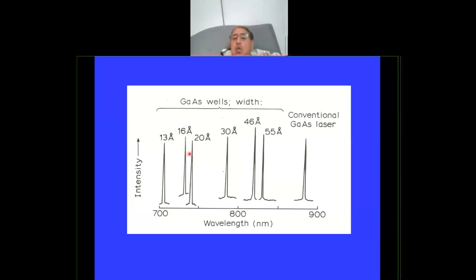Can you imagine if you're making, for example, red lasers or some kind of lasers and you must produce them in this wavelength, 700 nanometers. It means that you have to produce these lasers day after day with exactly the same thickness, 13 angstrom. But if you make only one mistake of 3 angstrom, and 3 angstrom is only one layer of gallium arsenide, one layer of arsenic, one layer of gallium, you can shift this wavelength. That means with the MBE system you can control these thicknesses accurately day after day. That's why it's very important for mass production, because you want to produce the same device day after day. And you can see the thicknesses are very, very small. If you make a small mistake, the laser would not emit at the proper wavelength.